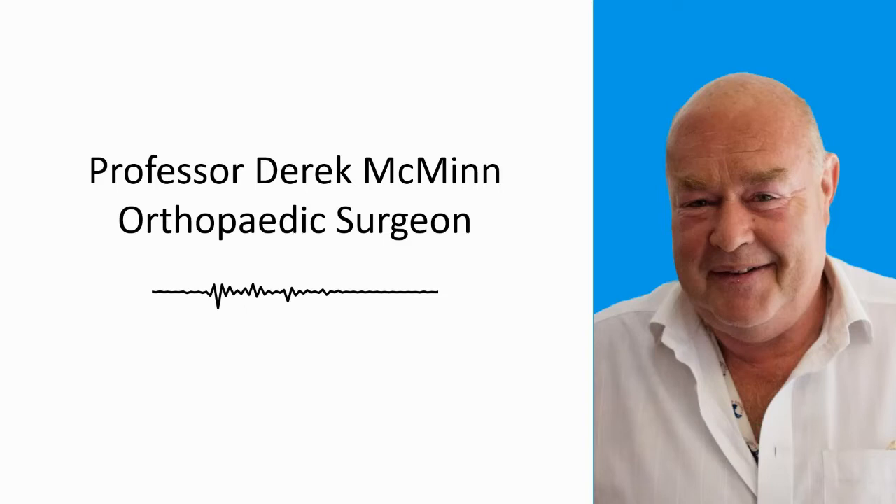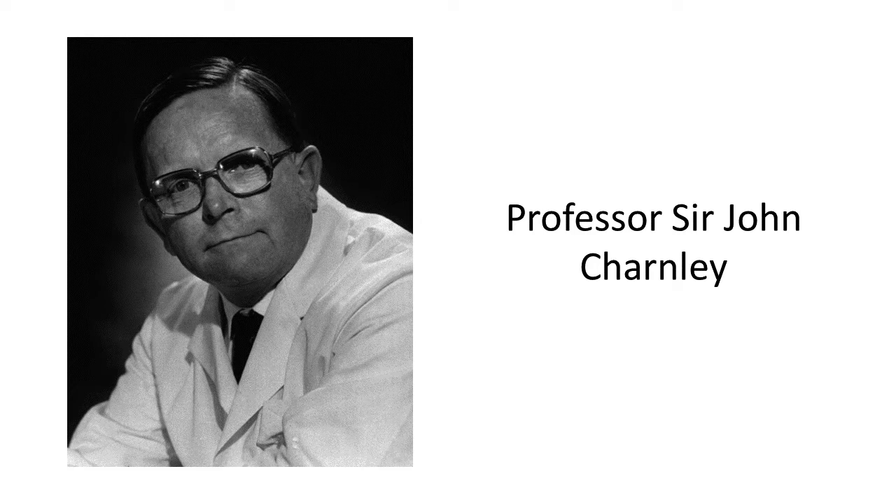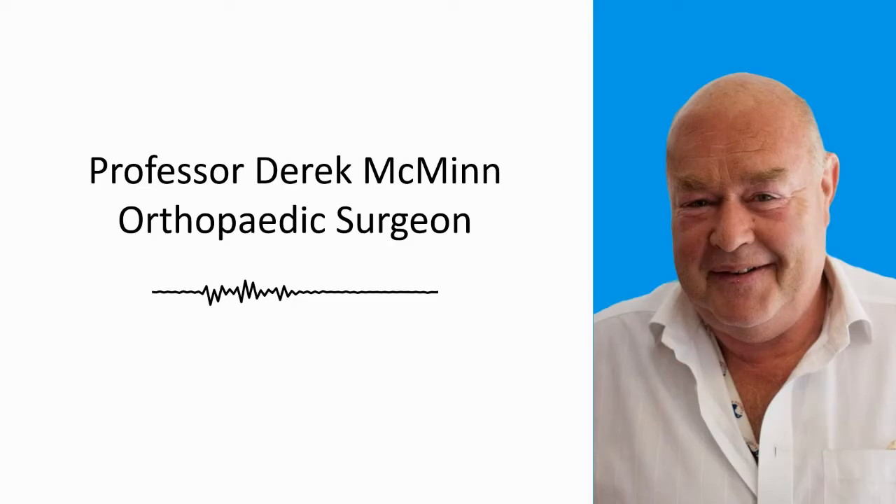With the essential lesion being loss of a couple of millimetres of articular cartilage in the femoral head and cup, it was inevitable that a surgeon-stroke-engineer would reach to coating the femoral head and cup with prosthetic materials. The first to do that was Sir John Charnley in the 1950s, and he used Teflon on Teflon. It only lasted a few months. Two layers of Teflon bound together and the cup and head moved as one, grinding against the acetabulum and producing lots of particulate debris. We had Wagner, Freeman, Amstutz and others going with metal or ceramic on conventional polyethylene. That didn't work.